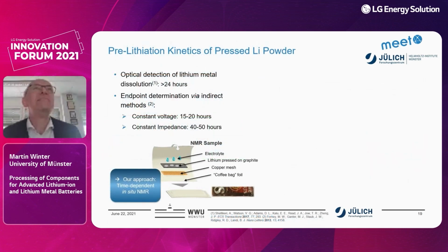Optical detection of lithium metal dissolution typically takes more than 24 hours if you do not apply any force, just physical contact. Then you have the endpoint determination via indirect methods. You look at the constant voltage. When does the cell have a constant voltage? It's maybe not so accurate because the lithium and the silicon graphite potential is not very different.